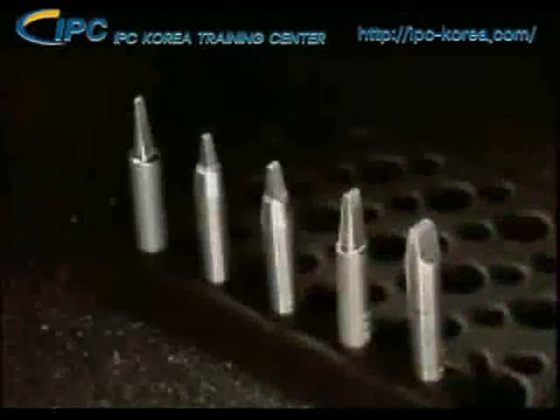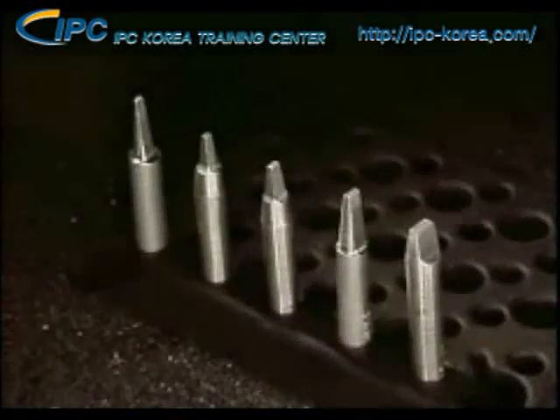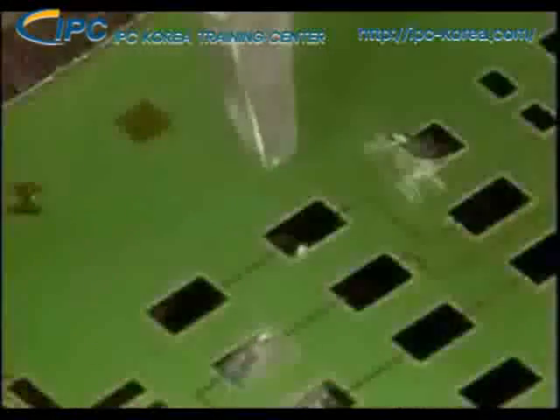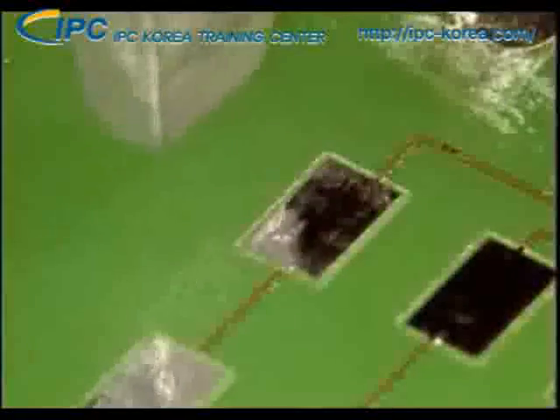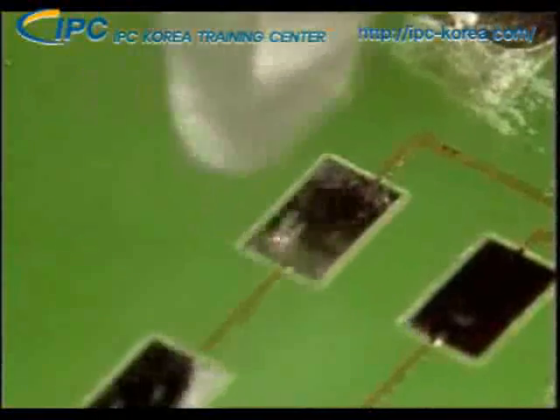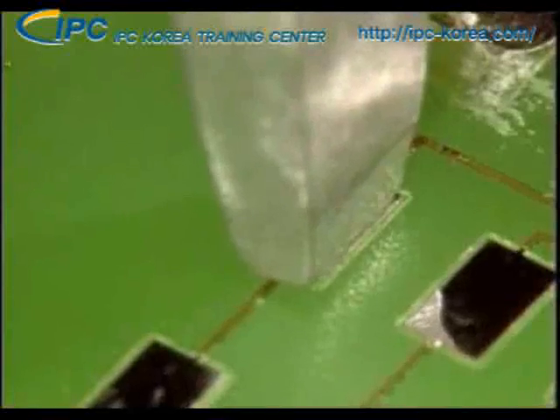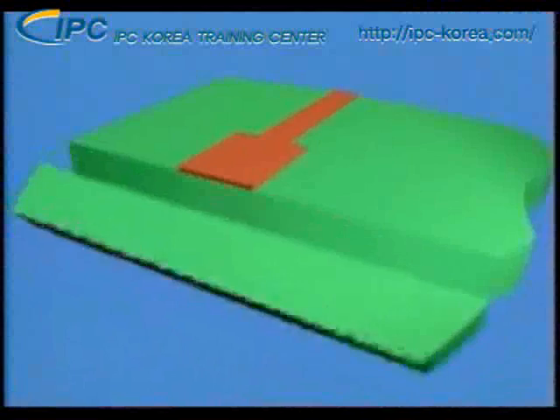Now let's select a soldering iron tip. Hold different tips over a land next to the one you're repairing until you find the right one. Try to match the tip size to the exact size of the land. If you can't find one the same size, use a tip size that is slightly larger than the land. Never smaller. You must have an even soldering all the way across the surface. The land will not solder at its edges if the tip is smaller than the land.